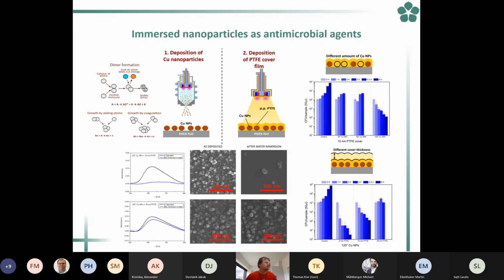So that was done, and these are not just only the antibiotics that are providing some antibacterial effects. These are also, for example, some nanoparticles that we used. For example, the copper one or the silver one. These effects are already known for a very long time. But what we try to do, as also shown here, is that we deposit the nanoparticles, then we try to immerse them in some matrix. Usually it is done again from some plasma polymer. For example, here it was from Teflon.